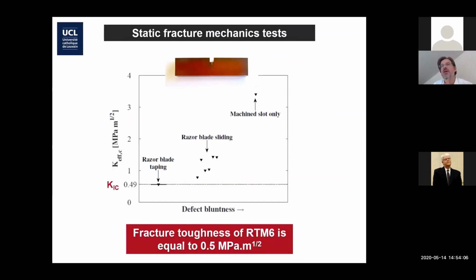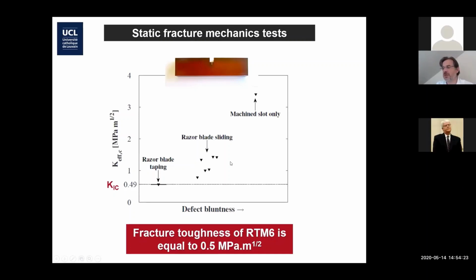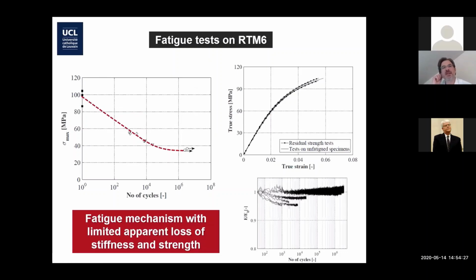We measure carefully the fracture toughness, and it's known in the polymer field, you have to be very careful in the way you introduce the pre-crack. And if you just use razor blade sliding and not tapping, you measure a fracture toughness that is twice on average the value of the real one, so very careful. And we perform fatigue tests, and the main message here is that if you do a tensile test after a long fatigue, you don't see much difference in the response. So the fatigue is not leading to a lot of reduction of stiffness or strength. It's only at the very end, you're generating defects and the material breaks. So the incubation time is very long.